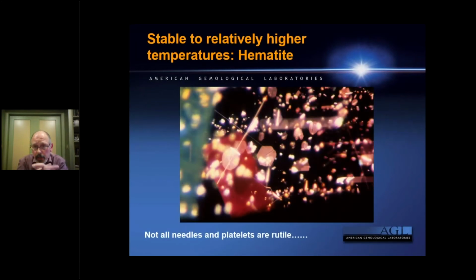One caveat I also want to mention as we go through these: not all needles and platelet type inclusions are rutile. Here's an example of hematite. This is an iron oxide. Iron diffuses much differently in corundum than titanium. This requires a much longer time period. John Emmett was describing the geologic time scale you need for dissolving or diffusing iron. So as a result, even heating at relatively higher temperatures, you're not going to be impacting needles and platelets of minerals such as iron oxide minerals such as hematite.